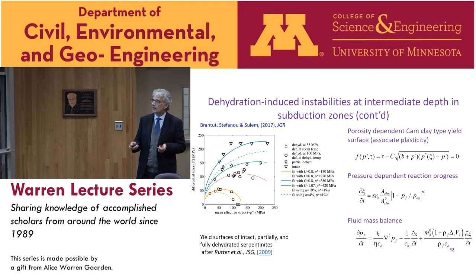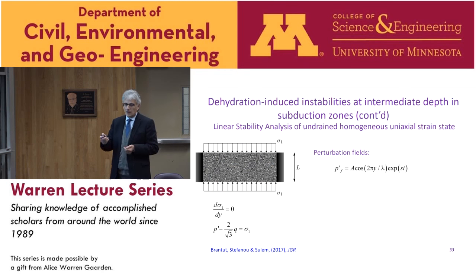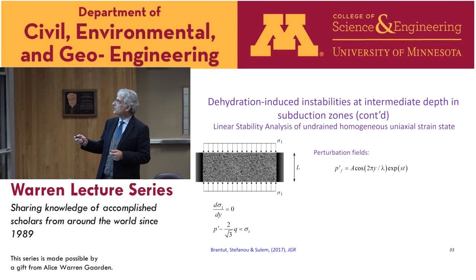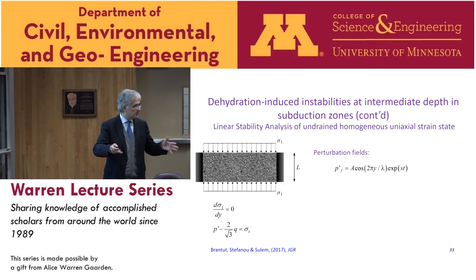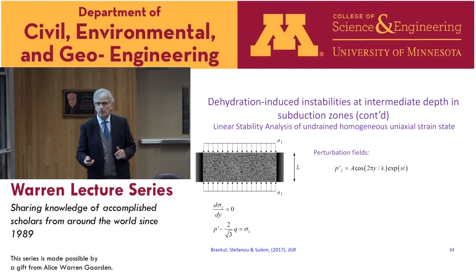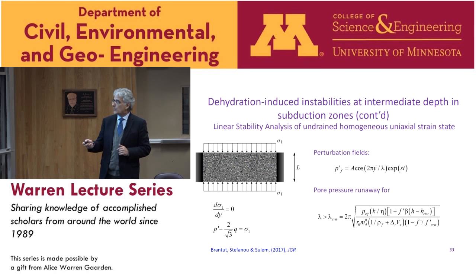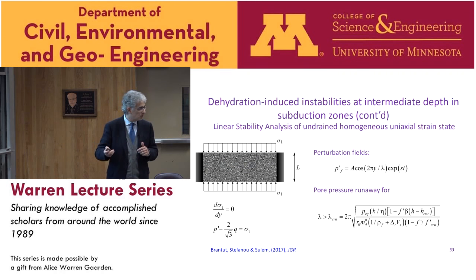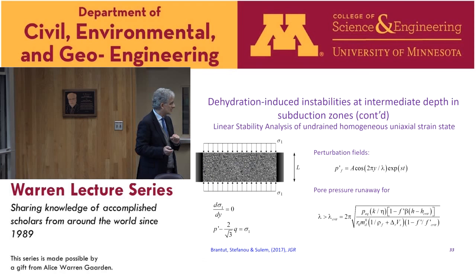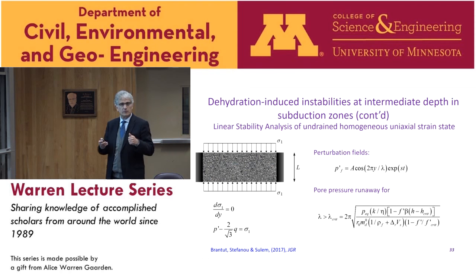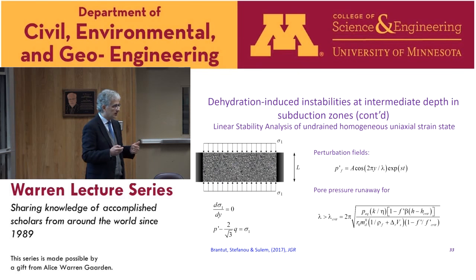To study the stability, in a simple problem, we consider a uniaxial strain problem. So it's like an oedometric condition. We imagine a slab which is going deeper. We perform a perturbation analysis, and like in the previous result, what we obtain is that at the instability conditions, all wavelengths greater than some critical value are unstable. So again, we have some threshold. Here we did not introduce any material length. It's done with a classical continuum, but we have some competing length between the diffusion length and the rate of the chemical reactions. And this gives the control length of the instability.